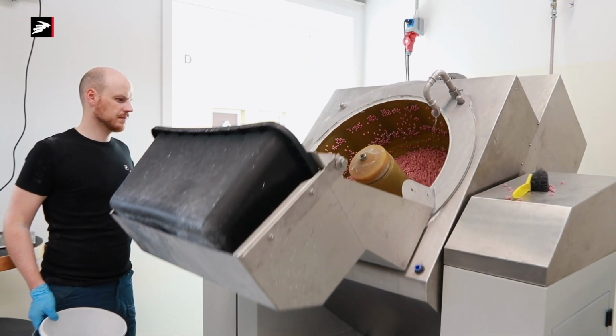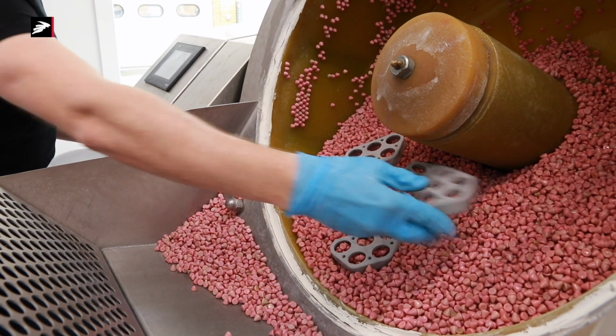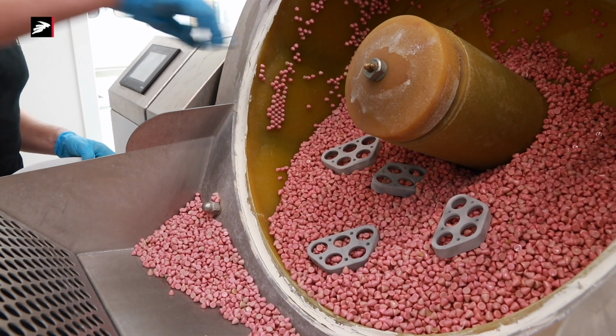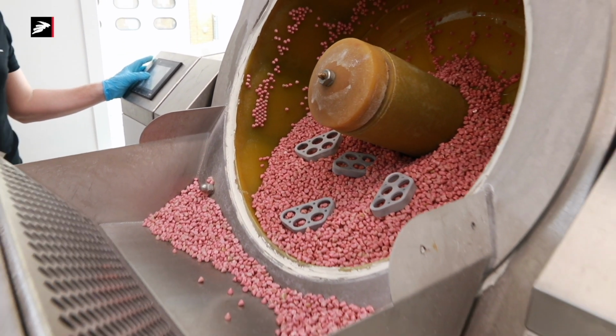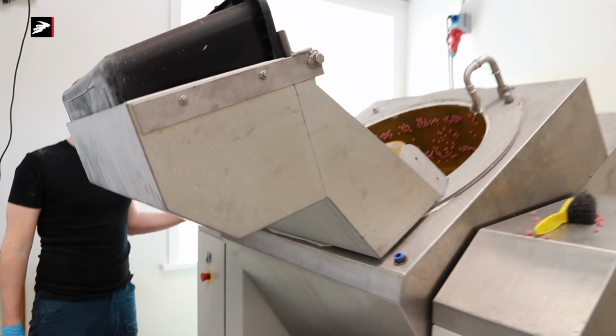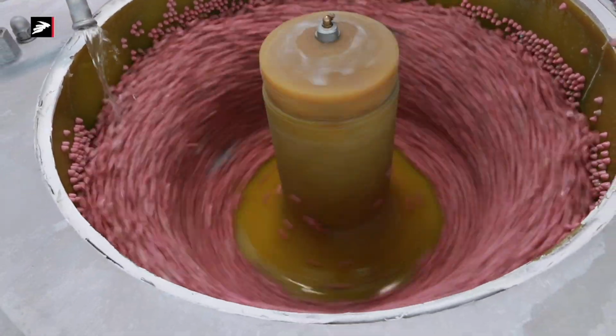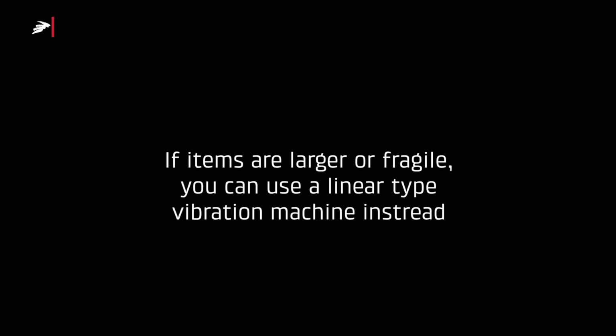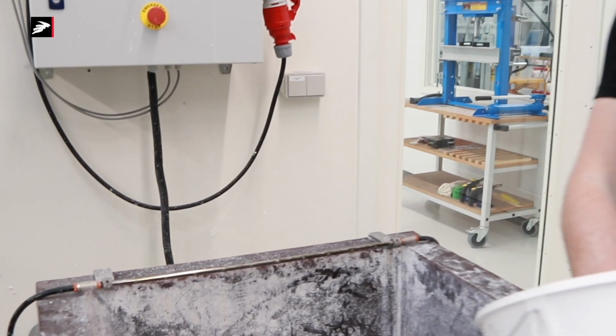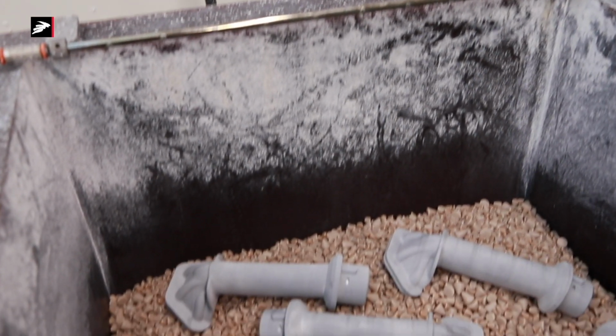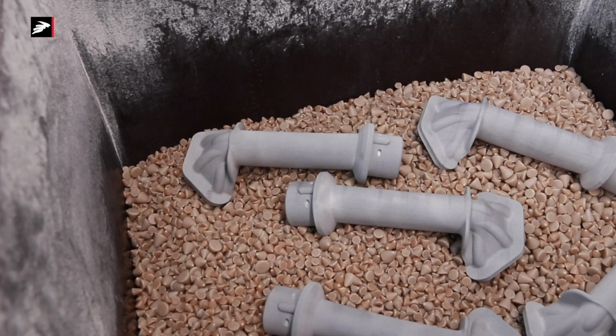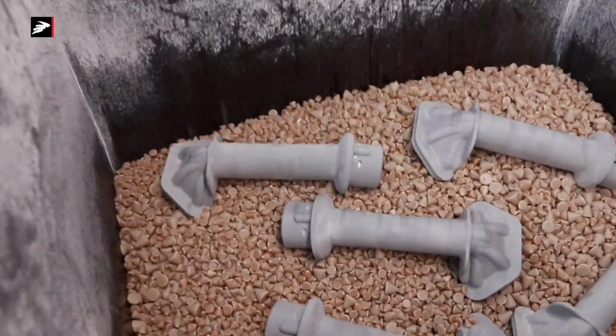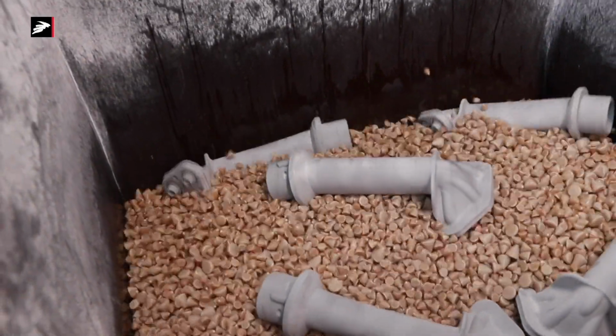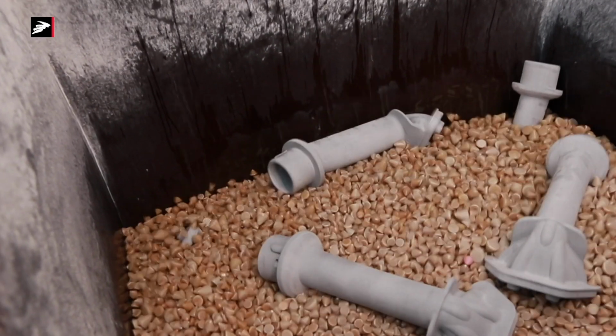Here we see how the items are placed in the deburring machine. Deburring of this type is really good for smaller parts because it has a really good abrasive effect, and because it moves the parts around so that all of the parts get uniformly deburred. On the other hand, if you have some quite fragile parts, then this type of deburring is not a good idea. Here the parts are put in, and with vibration they are moved around more gently. This also means that the part needs more time in this second type of deburring machine.